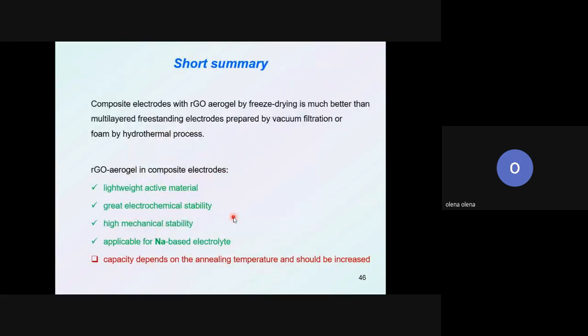So a short summary is like that: aerogel for supercapacitor electrodes is much better than vacuum filtration and hydrothermally obtained electrodes. RGO aerogel and composite electrodes give us the advantage to obtain lightweight active material and electrodes. Great electrochemical stability, mechanical stability. We can use sodium electrolytes, not obliged to use lithium electrolyte. But of course, capacitance strongly depends on annealing temperature and should be increased because this is our goal.